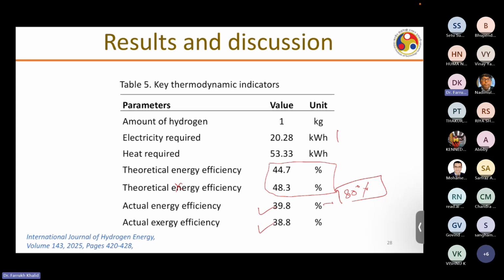As you closely look at it, compared to water electrolysis, typically in water electrolysis, in order to produce 1 kg of hydrogen, we all know that if it's a pure electrolysis process, you require around 50 to 55 kilowatt hours, whether you use a PEM method or AEM. However, in our case, we require only 20.28, which is around one third of that. The requirement of thermal energy is a little higher, but when you do the overall conversion, you find that our cycle is much better.